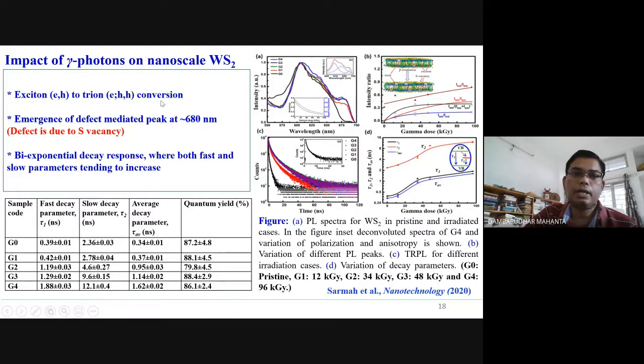And we found, after analyzing this area wise, that the exciton to trion conversion is possible in this particular system because of gamma irradiation.